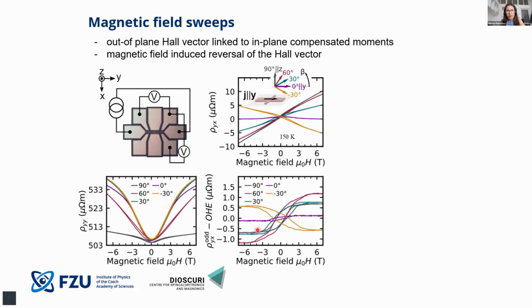which basically says that the signal is proportional to the out-of-plane component of the magnetic field, right? Because the in-plane component for basically the green and yellow is the same. However, the signal is changing sign. Therefore, it's the out-of-plane component which matters. However, it still helps us to have also the in-plane component.